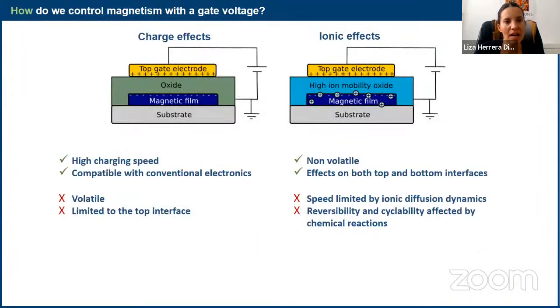So that said, how do we control magnetism with a voltage? There are different avenues that we can take. In principle, it could be charge effects, which we know well from field effect transistors in nanoelectronics. We have our material of interest, an oxide with a high dielectric constant, and a counter electrode. If we apply a voltage across this oxide, we accumulate charges at the surface of our magnetic film. The magnetic film being a nanostructure, it is extremely sensitive to what happens at the interface, as we know very well, in particular for perpendicular anisotropy, which comes from the interface. So with this charge accumulation at the interface, strong changes in the magnetic properties can be induced. And this is very interesting.